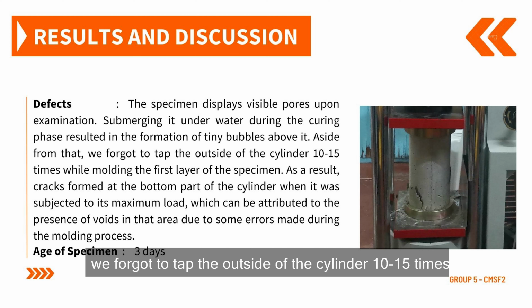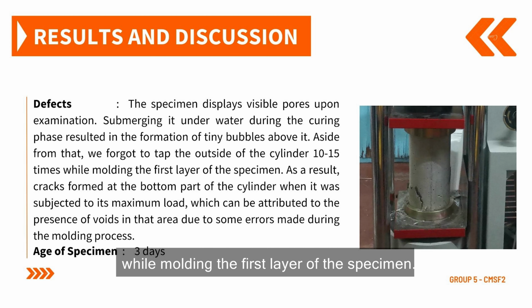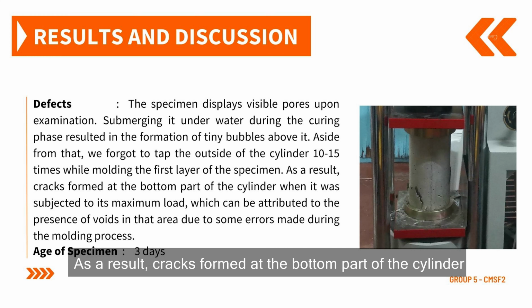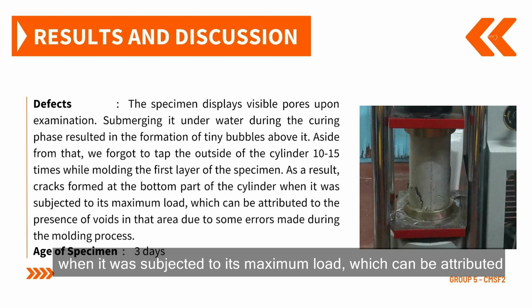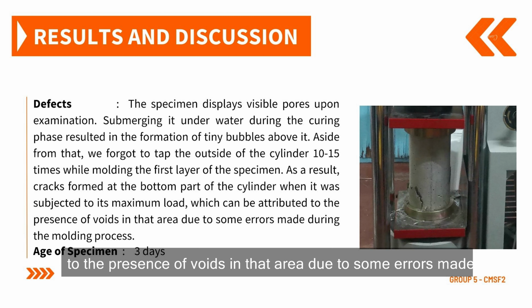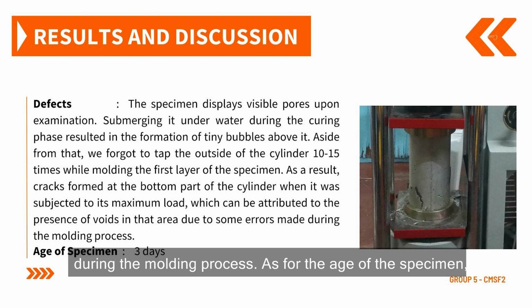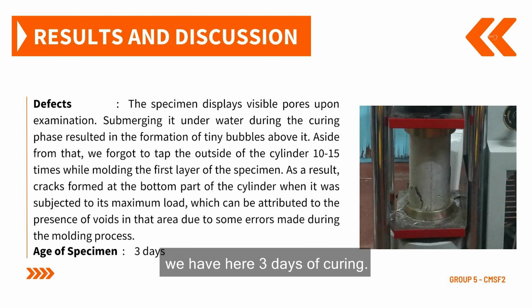Aside from that, we forgot to tap the outside of the cylinder 10 to 15 times while molding the first layer of the specimen. As a result, cracks formed at the bottom of the cylinder when it was subjected to its maximum load, which can be attributed to the presence of voids in that area due to some errors made during the molding process. As for the age of the specimen, we have here 3 days of curing.